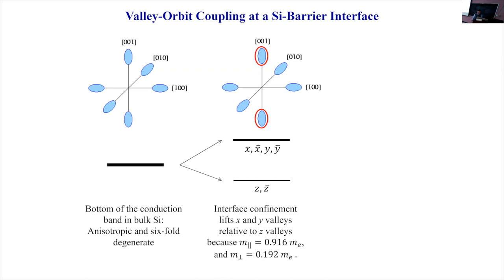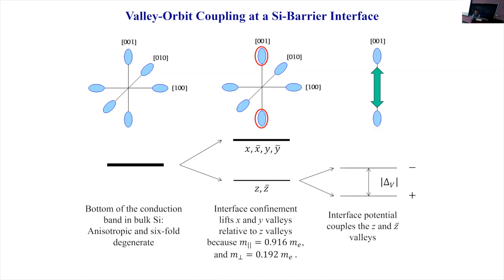Okay. And then because of the presence of the interface, the electron would scatter off that interface. That would also couple these two conduction band minima. Okay. And that gives you the so-called valley splitting. So this is the coupling between, let's say, the Z and Z bar valleys. That coupling is the so-called valley-orbit coupling. Okay, and that leads to a splitting of that degeneracy. Otherwise, they would still be degenerate, but because of the scattering off the interface, they are not degenerate anymore. You have the so-called plus and minus valley.